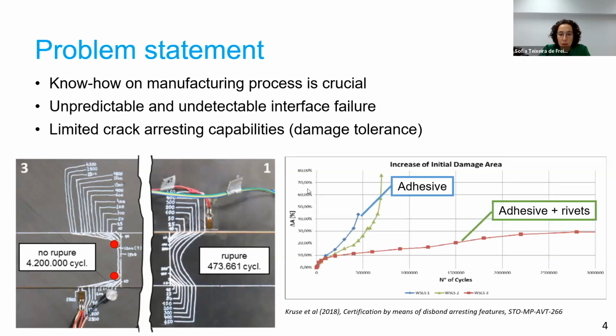What you see in the graph is the delta a, which is the increase of the crack length. So how does the crack propagate with the number of fatigue cycles? You see here that for the plain adhesive, we have a sudden, exponential increase of the crack growth.